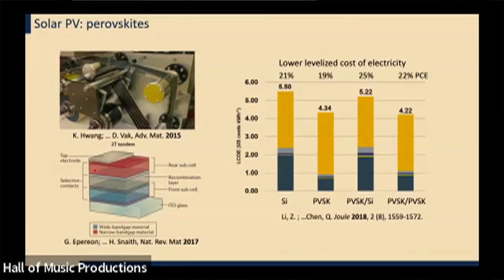And then from techno-economic projections, this is where things get interesting from a driving a greater supply of lower cost, low carbon electricity perspective. Folks have modeled how much can we reduce the levelized cost of electricity from solar when we move to these technologies that are more and more efficient. You see going from the left to the right across here, higher and higher efficiencies. And then in the final one, a reasonably high efficiency, but combined with a really low manufacturing cost. And you'll see here a projection for a further reduction relative to the existing state-of-the-art silicon technologies being achieved by these projected perovskite performance levels.